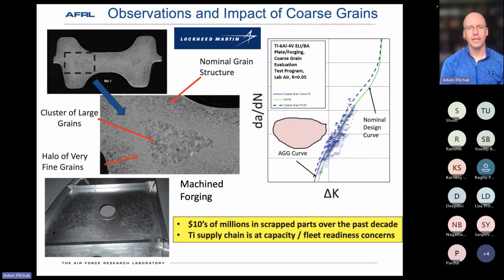The small crack effect is interesting when real cracks form and they're naturally initiated. They form kind of with microstructural dimensions. So if one of these large beta grains with its corresponding large colony inside forms a fatigue crack initiation site, the crack can grow essentially unimpeded for quite long distances, physically large distances. And some of the attributes of small crack growth are that they can grow at values of delta K that are below the so-called threshold for long cracks.